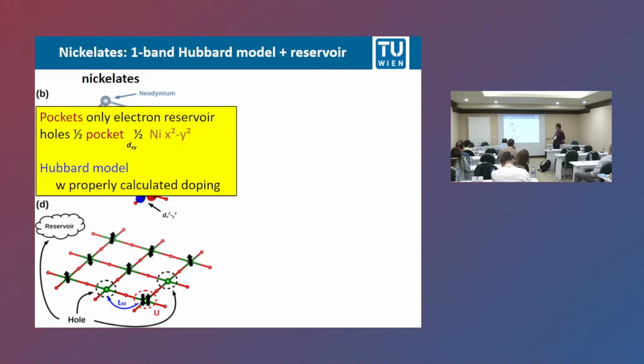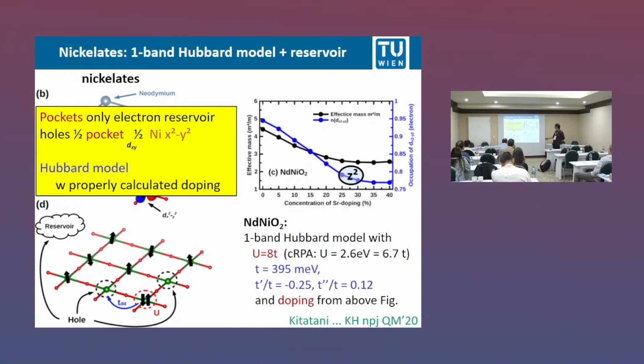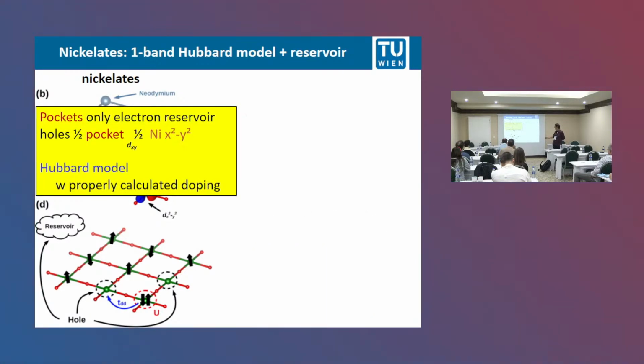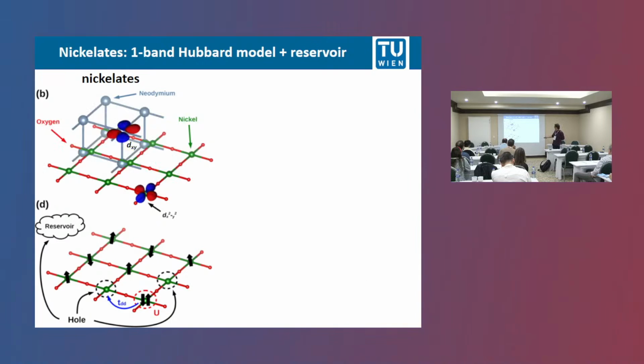So there's no hopping of electrons between these two orbitals. And therefore, as a first approximation, we can consider these two orbitals to be decoupled. Still, if they are decoupled, this A pocket plays a role, because if you strontium dope your system, you put holes into your system.